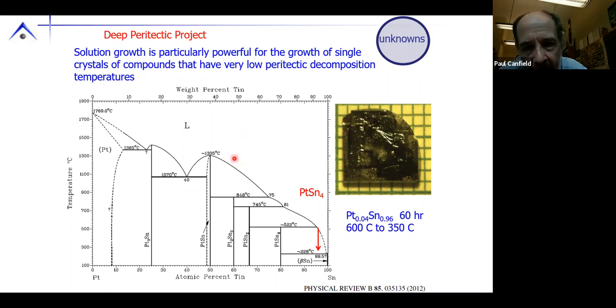If I cool this down, I hit this liquidus line, I start growing platinum tin. The liquidus line tells me what the composition of the liquid at a given temperature is. All this cooling, I'm getting more platinum tin and the liquid is becoming more tin rich, okay? Now, when I drop below this peritectic, I start growing platinum 2 tin 3, okay? And I still have a liquid that's becoming more tin rich. I'm now growing and it's getting more tin rich, and now I'm growing platinum tin 4, okay? That's how you read a binary phase diagram, okay?